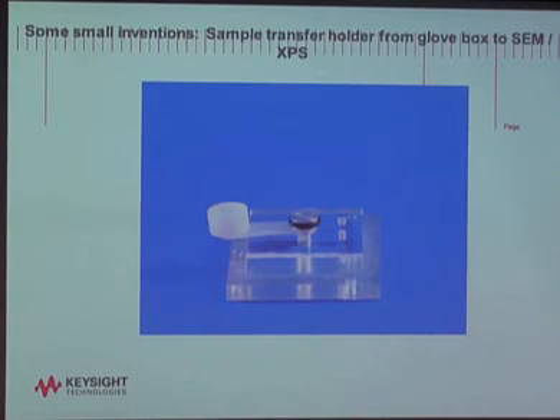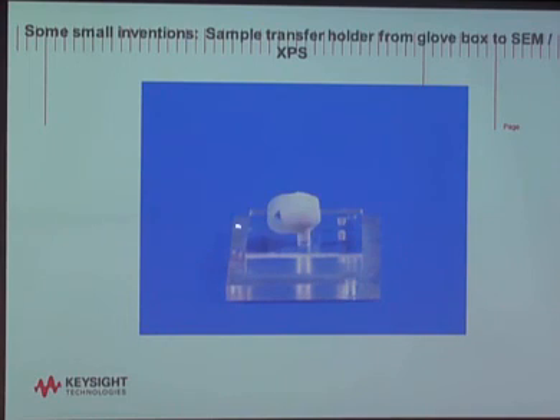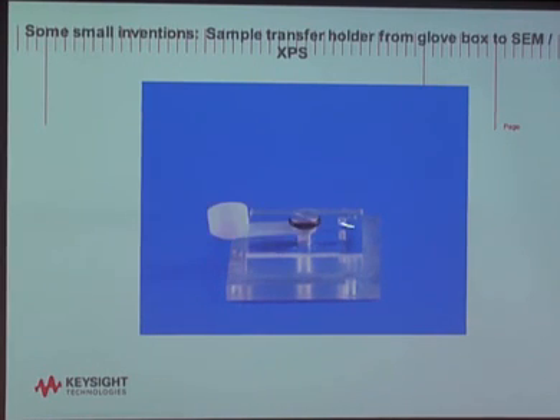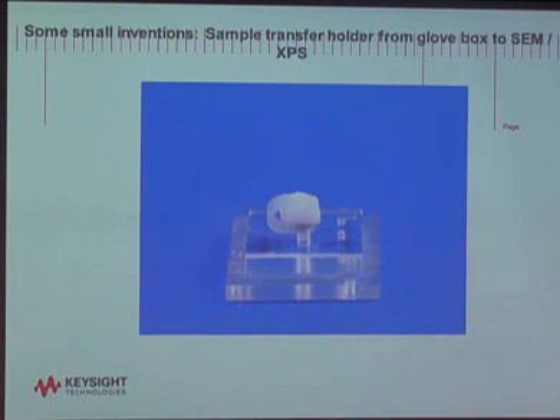I say, hey, don't use complicated solutions, because any complicated solution turns itself into a complicated problem and could ruin some graduate student's life. So I said, I'm going to think about it, and this is what I dreamed of. It's very simple, because you have a little cover here, and you have the sample holder, and you close the sample holder, and then there's a little latch here, right? And then you seal your sample in your glove box, and you put it in your SEM, and then you close the door, turn on your vacuum, and the whole thing pops out by itself. And that's a really cool application note, we should end now and let that be for Thursday, because I think that's really relevant to a lot of people.